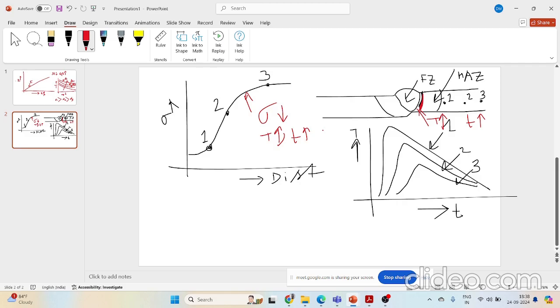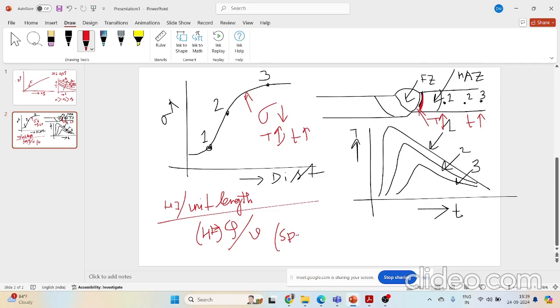Both the size of the heat affected zone and the retention time above your effective recrystallization temperature will increase with an increase in heat input per unit length. What is heat input per unit length? I'll be denoting this as Q by V. Q is my heat flux, and this is my welding speed, right? The ratio of total heat input to the welding speed is known as heat input per unit length.